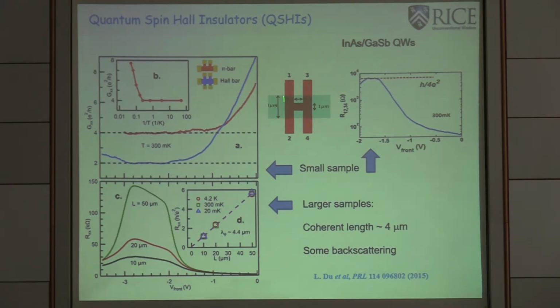And also one can make such small devices, 1 micron by 1 micron. This is the so-called H-bar device. Now, if you pass current here and you measure voltage here, you can get a non-local transport. And non-local transport is supposed to give you a quarter of h divided by e squared for the resistance, which is 6.4 kilo ohm.